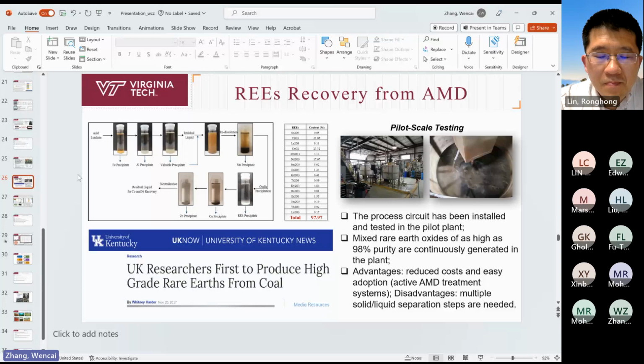So they need to add some alkaline to increase the pH value of AMD, and then you can discharge it. Otherwise, you will be punished if you directly discharge it. What you can do is incorporate this kind of precipitation process into the existing AMD processing. You just control the pH, and you collect the precipitate in a certain pH range. And the mining companies will pay the alkaline cost for the precipitation. So in a word, if you have AMD with rare earths of a few ppm, for example 5 ppm or 10 ppm, it can make the process economical. That's based on the mining companies being willing to pay the cost of the alkaline.